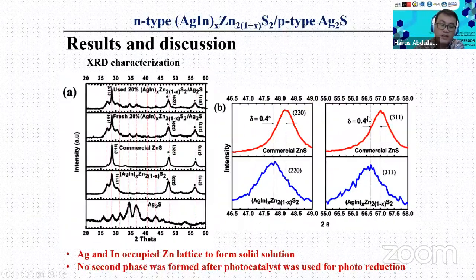Okay, then we try to analyze the powder with the XRD characterization. Then we see that all of these patterns basically show the major phase of ZnS, with a very minor peak of Ag2S. So we confirm the formation of two phases, right? One is the ZnS phase, doped with the AgIn, and then the other one is Ag2S. And we try to prove that AgIn is already doped into the lattice of ZnS by using this XRD pattern.